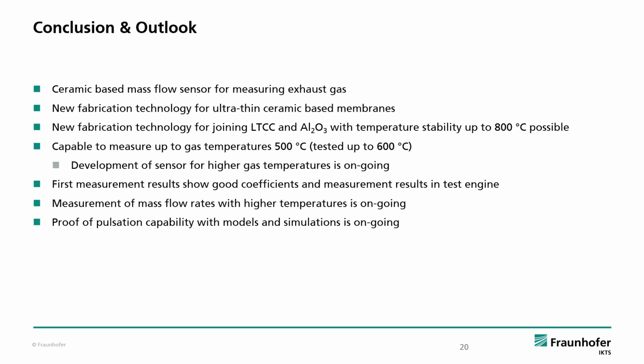I presented you that we can measure mass flow with this innovative sensor up to gas temperatures of 500 degrees Celsius. We tested it as well up to 600 degrees Celsius in an initial test. The development of sensors for higher gas temperatures is ongoing. Our first measurement results showed good coefficients, and we could prove the functionality in initial measurements in exhaust gas. In future, measurements with higher gas temperatures are planned, and as well the proof of pulsation capability with model simulations and in tests.